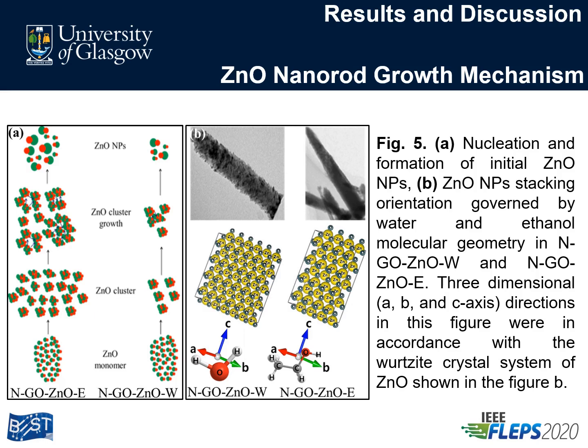As we know, the dielectric constant of water is higher than ethanol, therefore, higher zinc oxide monomer solubility in nanorods prepared in water solvent has led to its supersaturation reduction and subsequent nucleation rate. On the other hand, the decrease in surface energy due to a better ethanol-zinc oxide interaction, the relatively higher zinc oxide stability in nanomaterial prepared in ethanol resulted in a massive supersaturation and increased nucleation rate.